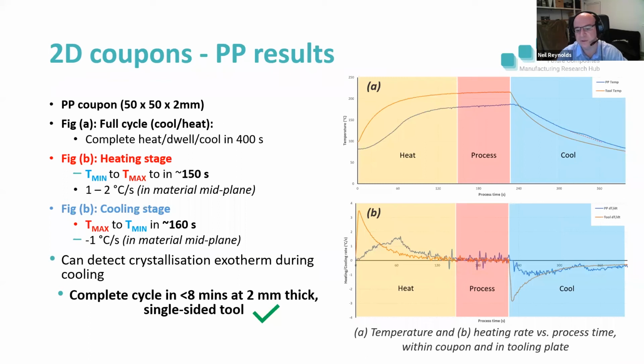The bottom right graph shows us the heating and cooling rate we achieve at the tool surface and in the material. Because the materials are a relatively good insulator, in the mid plane of the material we're only seeing heating and cooling rates of about 1 degree a second. What's interesting about this, on the right hand side in the cooling stage in the top graph, you can see hopefully a little bump, which is actually the crystallization exotherm that occurs during cooling of the polypropylene. And we think this is quite interesting.